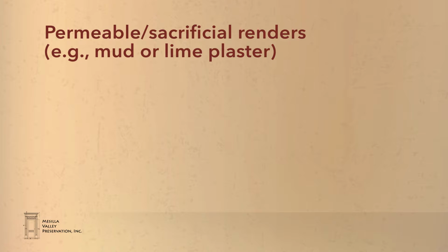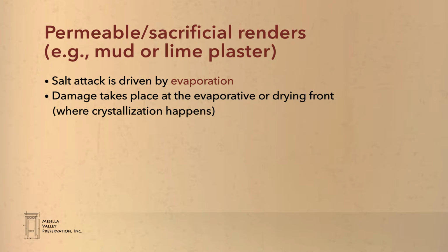People often worry about moisture, and yes, moisture is a part of the vicious cycle that can lead to salt attack. But as we've seen, moisture alone is not capable of doing the damage that we see with salt attack. Instead, the destructive phase of salt attack is driven by evaporation. Specifically, the damage takes place at or near the evaporative or drying front, where salts crystallize as moisture evaporates.